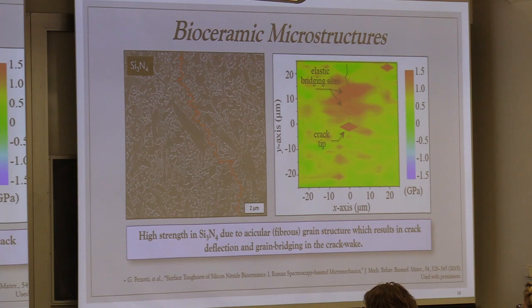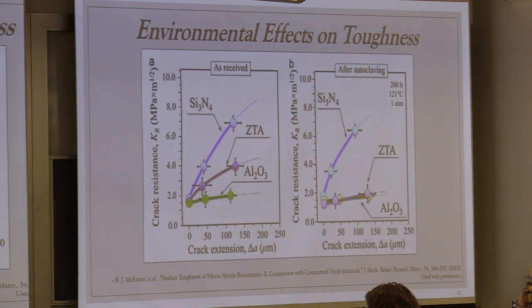And to accentuate that, what I'm going to show you here is a study which was performed to look at basically indentation toughening of three materials: alumina, which is this low material here, zirconia-toughened alumina, and silicon nitride. So these particular curves represent crack resistance, or what's called R-curve behavior. And R-curve behavior is the resistance to continued propagation of a crack as it begins. So as the crack begins to extend and grow, the resistance actually increases, particularly in silicon nitride, because it's being constrained by these bridging grains. But so is the ZTA material. But remember the difference between the two? One is mechanical based and the other one is chemical phase based.